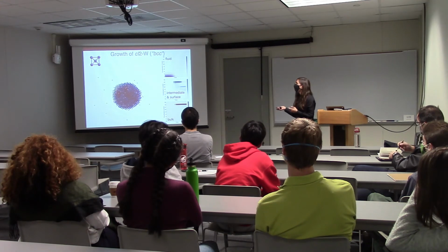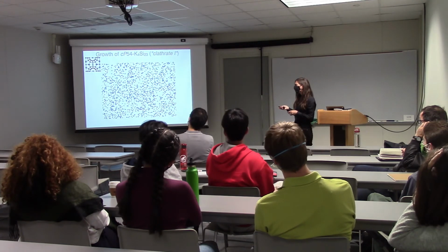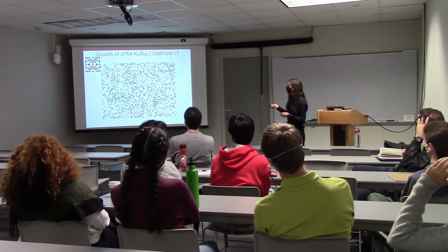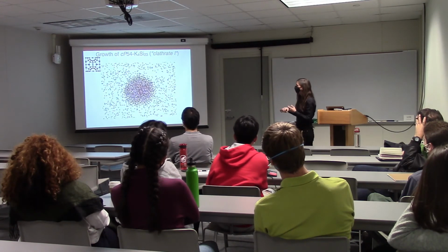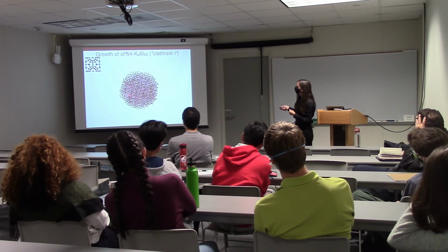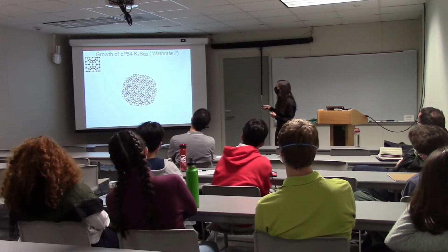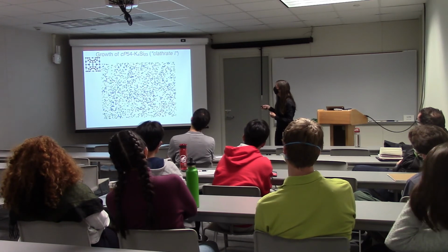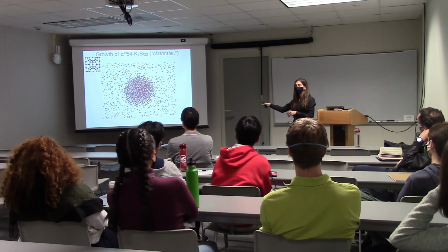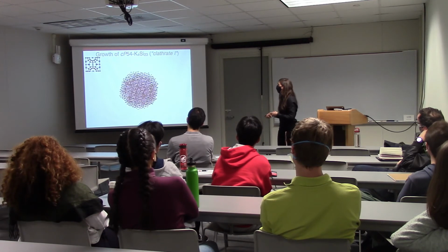What we can do as well is we can do this for the clathrate, where we have 5 different crystal positions. So we have to apply a higher number of clusters, and we can still see we have just a gas. We have a droplet form in the gas. But then the crystal that forms has all those different types of positions, represented by different colors, that actually occur in a periodic way. So you have the same color pattern in every unit cell. That's because the order parameter is capable of distinguishing the different local environments from one another, different crystalline local environments.